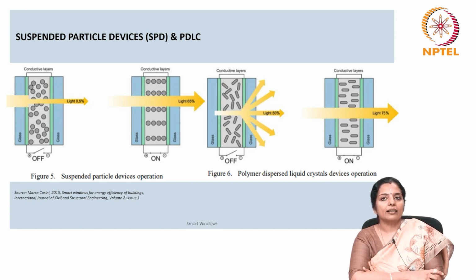Typical ranges for light transmission and solar heat gain in transparent and opaque states are VLT of 65 to 0.5% and SHGC of 0.57 to 0.06, with switching times of a few seconds. The device requires around 100 volts AC for operation and has power requirements of 5 watts per meter square for switching and 0.55 watts per meter square for maintaining constant transmission.